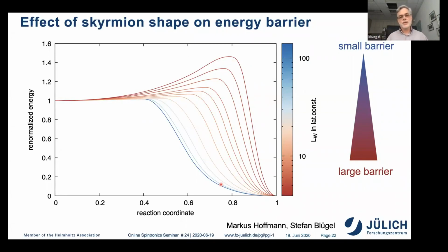So that means, as I told you before, you need the Dzyaloshinskii-Moriya interaction to stabilize this Skyrmion. But if the Dzyaloshinskii-Moriya interaction is small, your Skyrmion is small. But if you now make your Dzyaloshinskii-Moriya interaction large, your kappa becomes small. And if you make the domain wall small, the barrier is large. So a large DMI is valuable for the barrier. But unfortunately, you are in the regime where your radius quickly changes with respect to inhomogeneities of the material. So it's a very, very fine-tuning of the material to get the proper Skyrmions, which are stable, have the right size, and move fast.